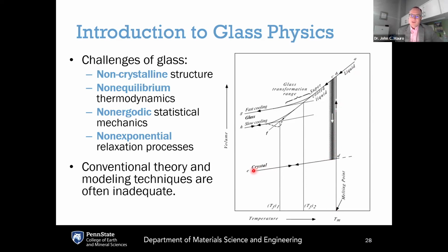This is what happens in equilibrium. However, crystallization takes time because it takes time for the atoms in the liquid to flow into just the right arrangement in order to form that crystal. And if you cool the liquid fast enough, you can actually avoid crystallization. And when that happens, you get what's called a supercooled liquid. A supercooled liquid is a metastable state that refers to any liquid that is cooled below its normal freezing point.